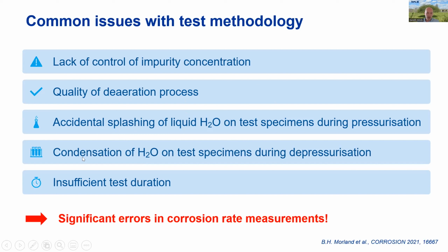Similarly, when we're cooling down the autoclave and depressurizing it at the end, if we're not careful and we don't do this properly, we can get water condensing on the specimens and adding additional corrosion that isn't realistic to the apparent corrosion rate. And finally, if the test is not long enough, we can fail to make an accurate measurement of corrosion rate. So all of these things add up to what we've seen in our literature review, that we have a very big range of corrosion rate being measured under what are nominally identical test conditions. And this is a problem for making decisions and for consensus among the research community.